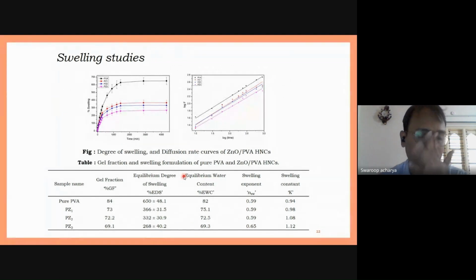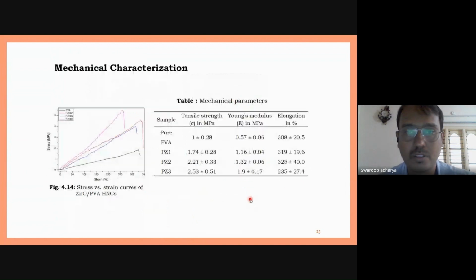The swelling studies have also shown a good amount of gelation, as well as equilibrium swelling water content, and other things have been noted here. Mechanical properties have also been studied, and it is shown that the tensile strength and the Young's modulus have moderately increased, with a small decrease in the elongation percentage. This means that there are not many variations in the mechanical properties.